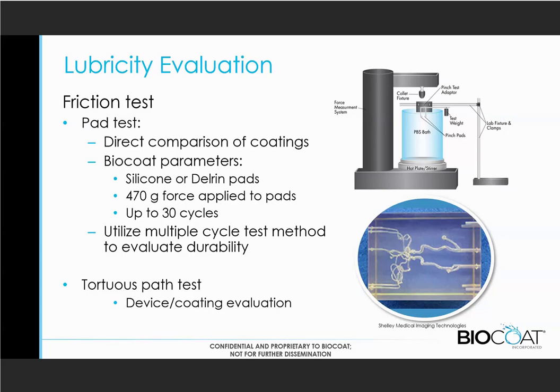The initial friction gives you a sense of what that coefficient of friction is. As I said, we're applying 470 grams. Best in class ones are below 20 grams or even 10 grams sometimes. And then on those multiple cycles, you're looking for good durability, so that basically that force is not changing over time for those different cycles.